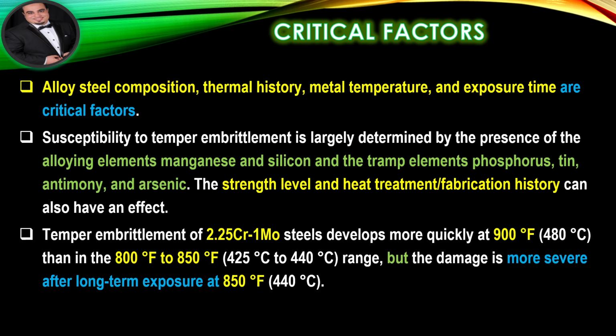Temper embrittlement of 2 1/4 chromium, 1 molybdenum steels develops more quickly at 900 degrees Fahrenheit than in the 800 degrees Fahrenheit to 850 degrees Fahrenheit range, but the damage is more severe after long-term exposure at 850 degrees Fahrenheit. Please note that some embrittlement can occur during fabrication heat treatments, but most of the damage occurs over many years of service in the embrittling temperature range.